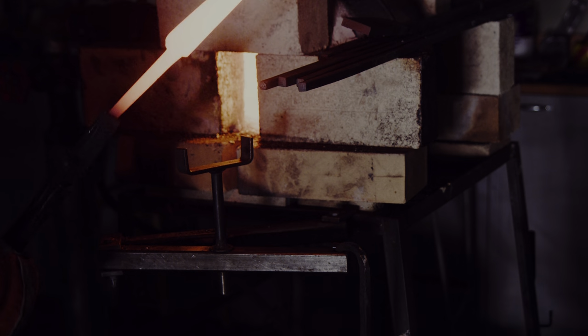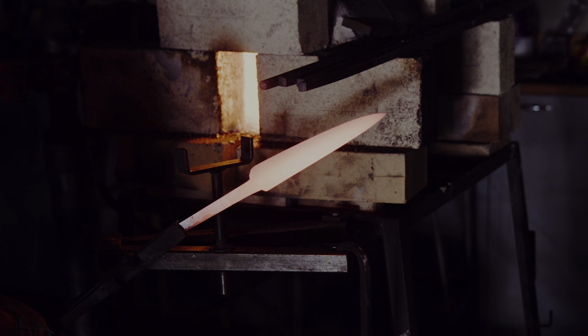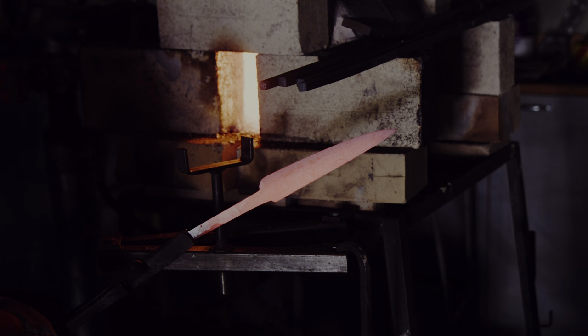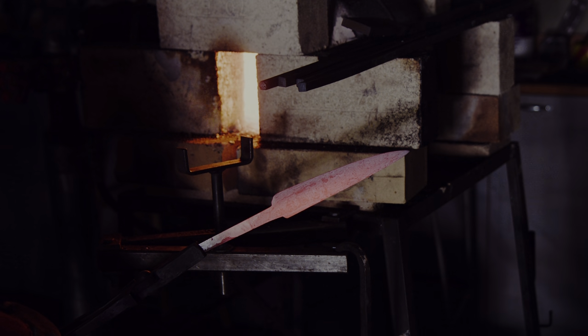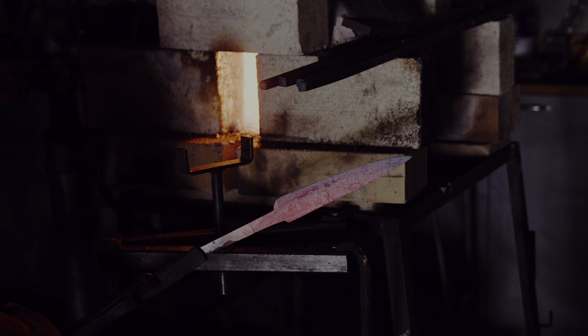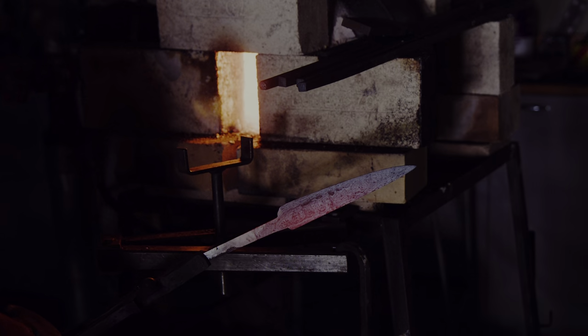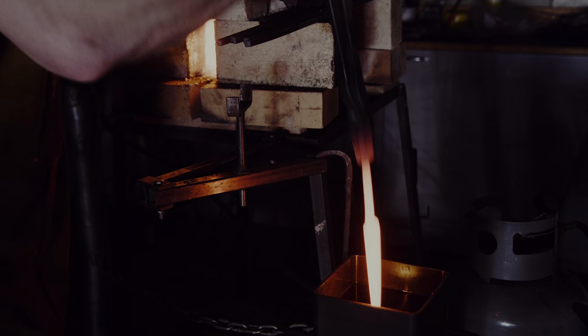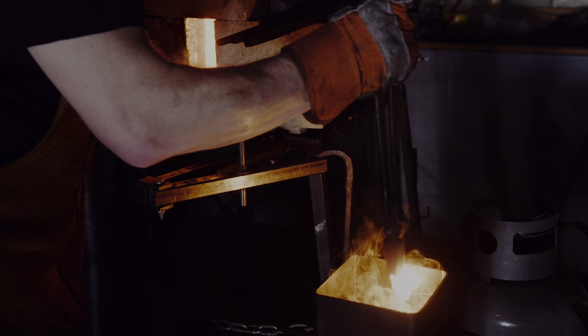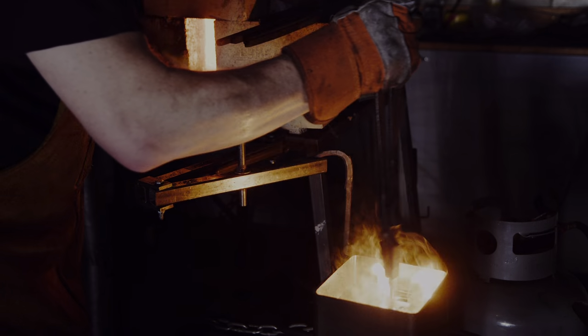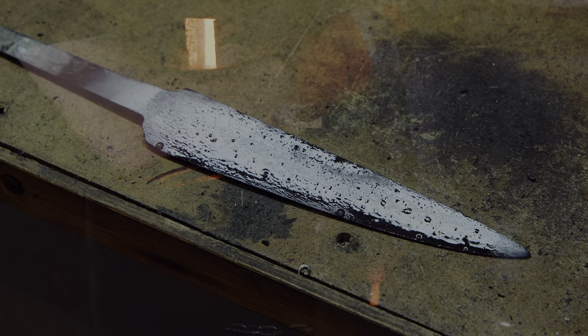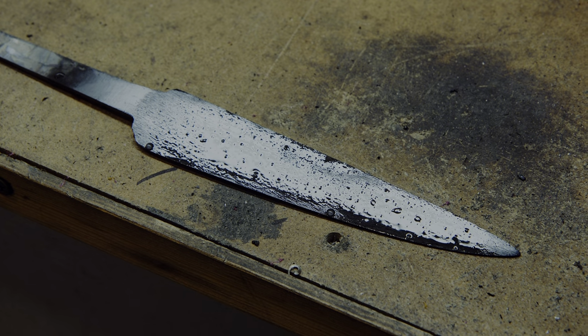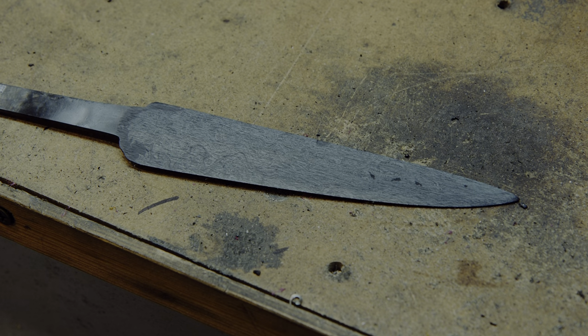Before heat treating, I normalize the blade one more time and let it slowly cool down. Once it no longer glows, I'm putting it back in the forge and then quickly plunge it into my high-speed quenching oil. Usually after quenching, the pattern in the steel is easily visible. So let's take a look. And of course, this looks much nicer in person, but I'm trying to get a good angle on this video.